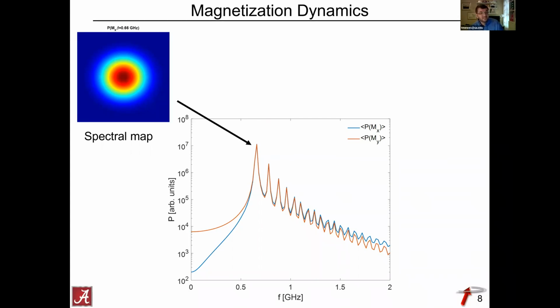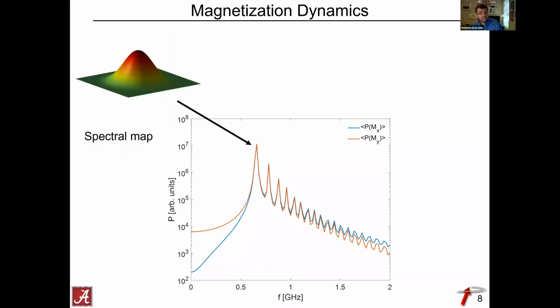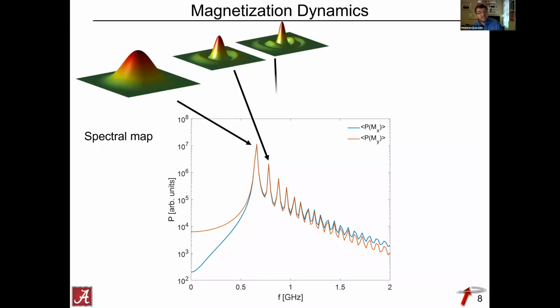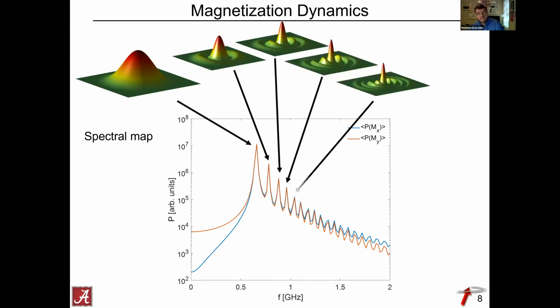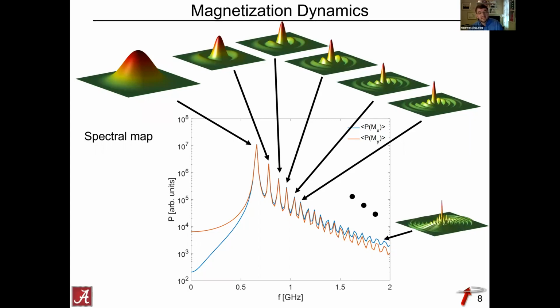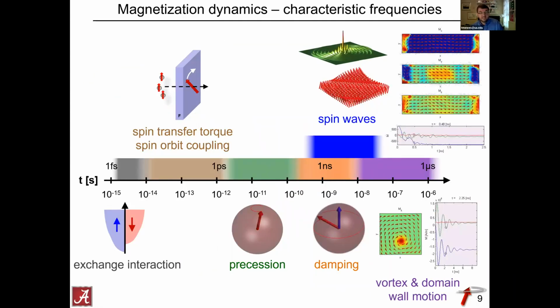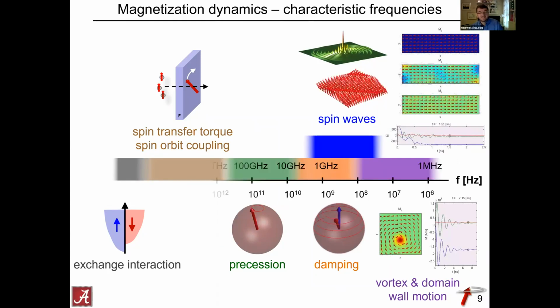And you can show this as a color-coded map, or you can show it in 3D like this. And then you can go through the different mode profiles that you see. Essentially what this tells you is that in this time domain signal, you had contributions from all these different modes that exist in this disk. And that led to this fairly complicated time evolution of the magnetization as it relaxes back to its minimum. So then, instead of looking at things in the time domain, we can simply look at things in the frequency domain. Obviously, nothing really changes. We're just changing the axis here.